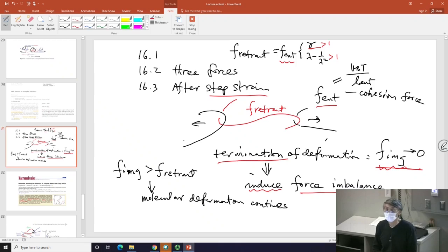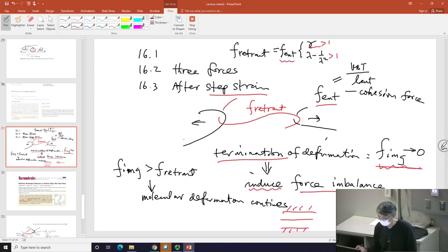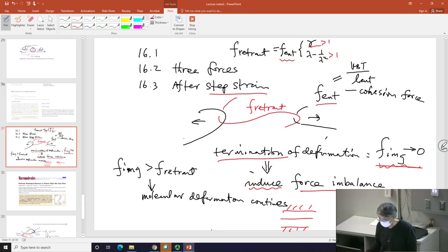The termination induced force imbalance. And we argued in the limit of B over H not being small, you can have this horse race producing a winner. In other words, some layer will disentangle first, the other layer will not. And then consequently, the system takes advantage of that breaking layer and starts to recoil microscopically, producing the motions. So we have a fairly good understanding of that now.